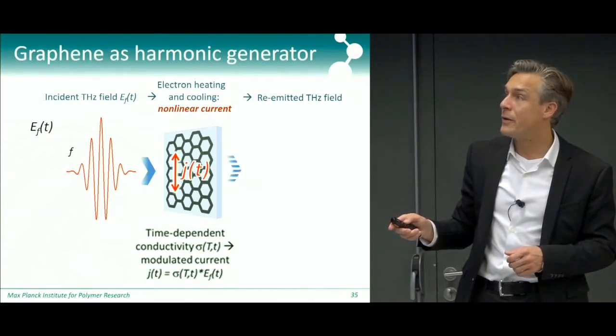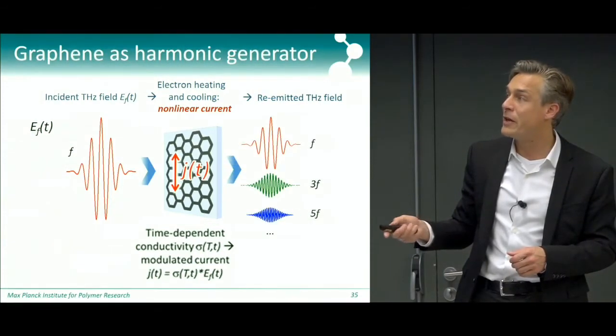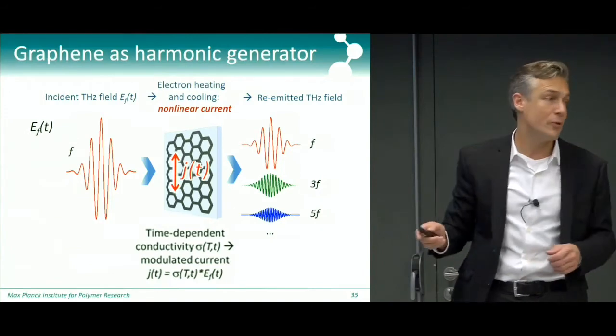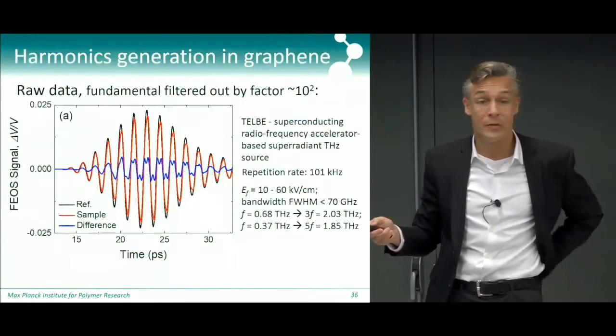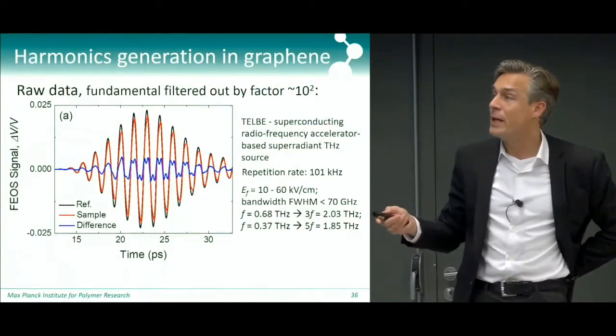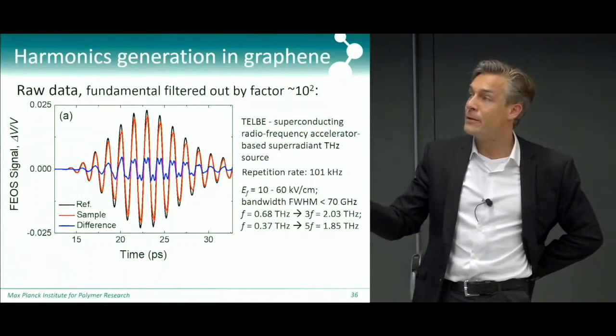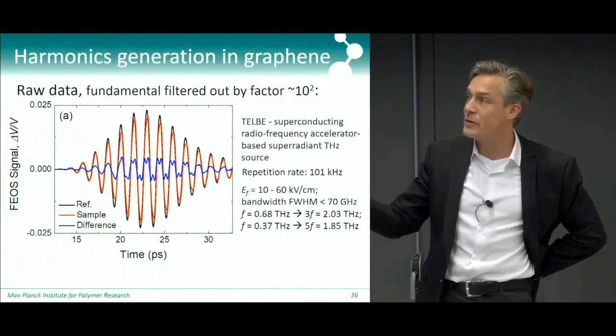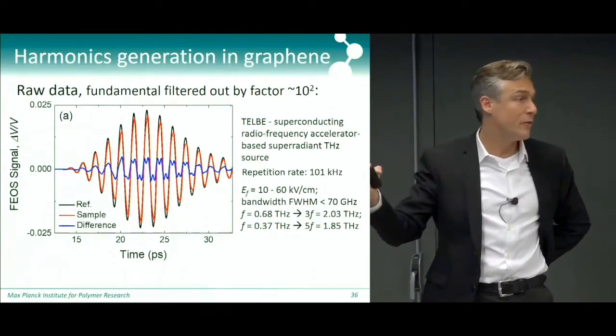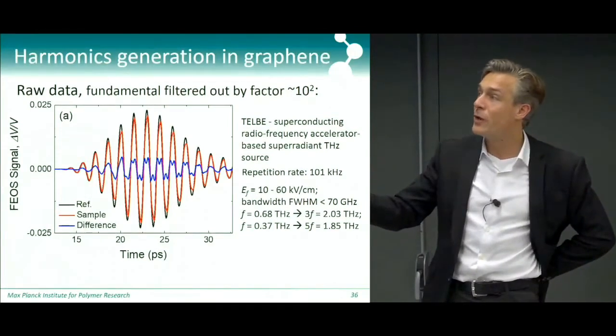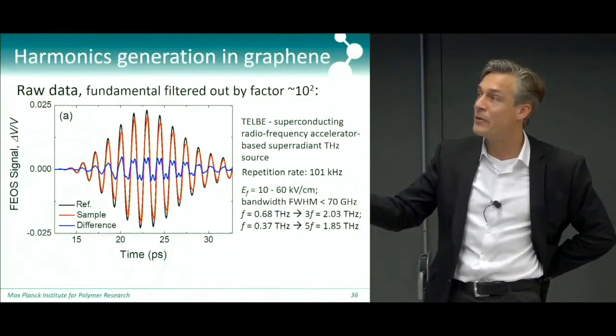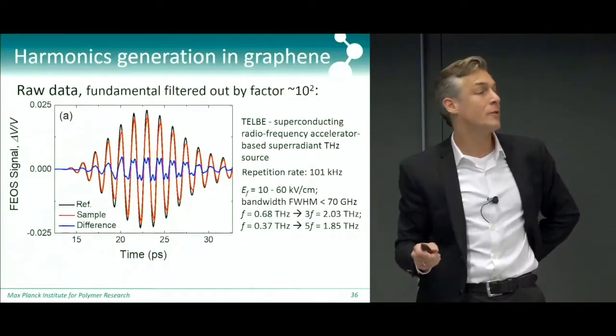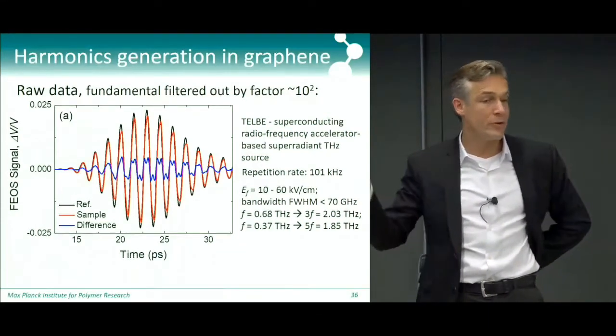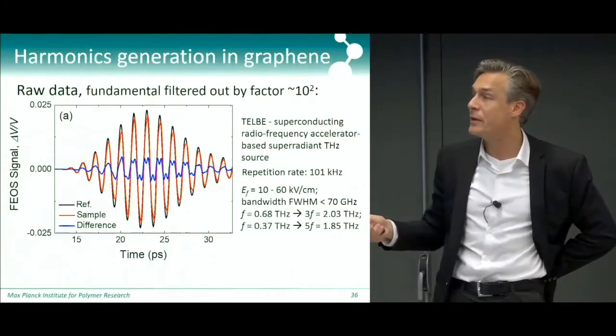And so this is what we then see: actually not only the third harmonic, but I'll show you also even the fifth harmonic and the seventh harmonic of the incident field. The raw data actually already shows you this. The black and the red are measured at different incident field strengths, and the blue that you see here is the difference, and you can see the harmonics in the signal itself. So this works extremely efficiently.